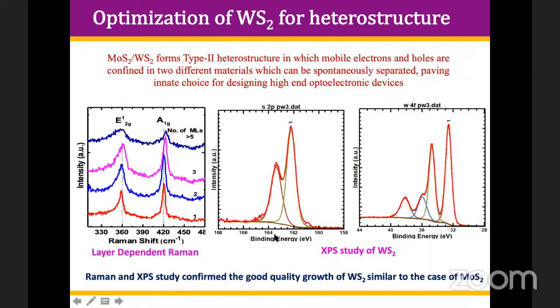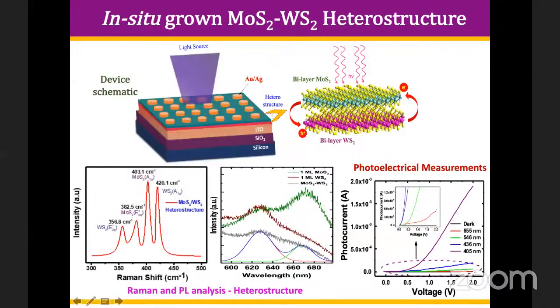So the number of shots required to grow WS2 is more. I can quickly go ahead now very fast, because these are just the characterization tools which I already discussed at the time of MoS2. So in this case, you can just compare. Just see here, this is a monolayer, 2-layer, 3-layer, and 5-layer system of WS2. And these are the XPS spectra, which clearly show that only 2 peaks are there, and no impurity is present in the WS2 systems.